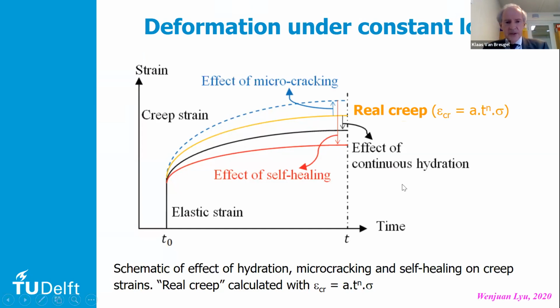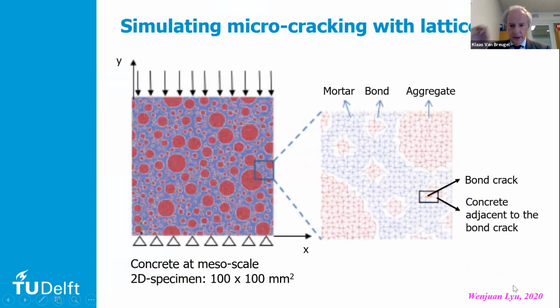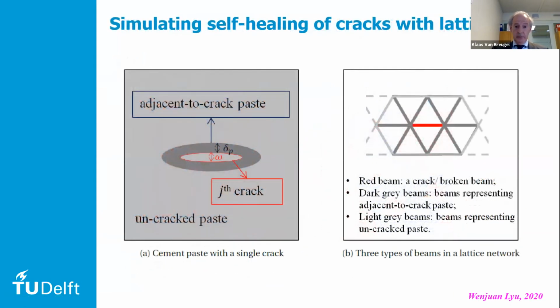So it would be interesting to see whether it works like that and if we can model that. Well, that has been the work of Wenjuan Lyu. She did a study a few years ago. She said, okay, I have here the concrete, on the mesostructure of the concrete. I simulate the performance with a lattice model, and I assign to the cement paste the possibility to crack, but also the possibility to self-heal.